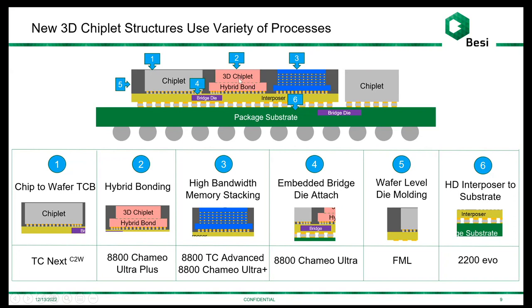But it's important to point out that even if you have hybrid bonding, you still have to get, at some point, those signals out to other functional blocks in the system. And that typically requires some kind of flip chip interconnection on at least one side of this hybrid bonded chiplet stack. Typically that flip chip connection will be to some kind of an interposer, either a functional die like Foveros, or a functional silicon interposer, or it could be any other kind of interposer. It could be a glass interposer, it could be an epoxy interposer with embedded bridge die. A lot of different possibilities.